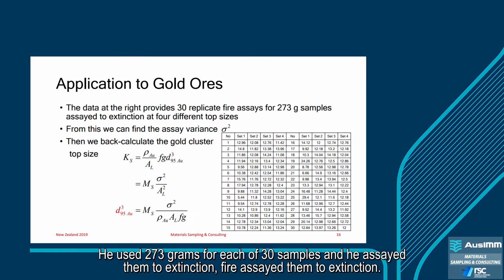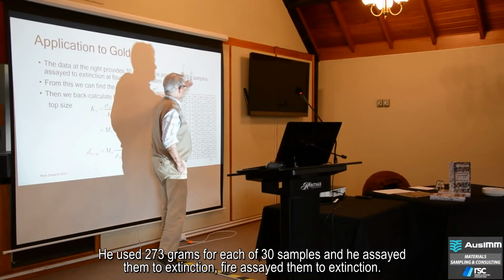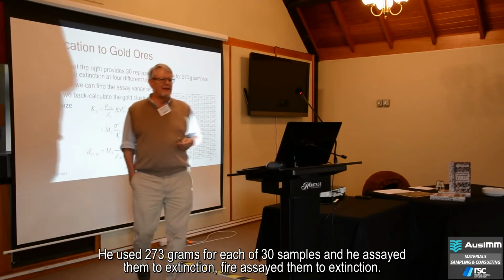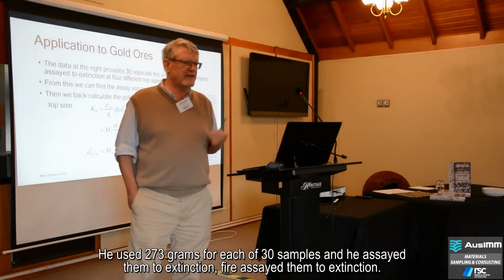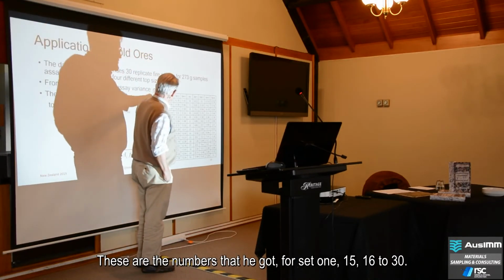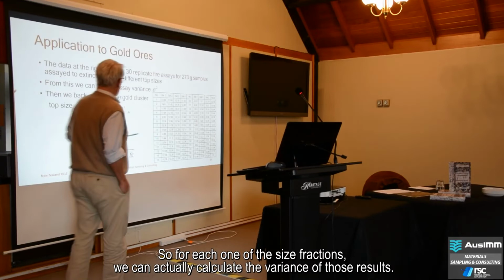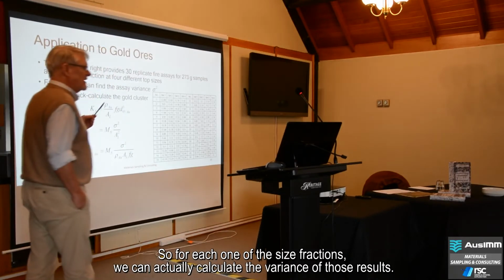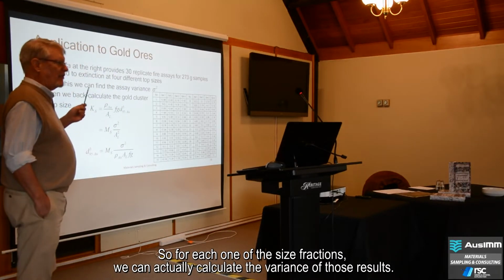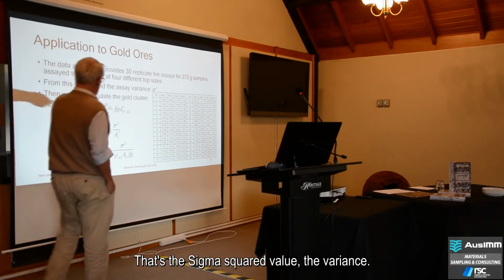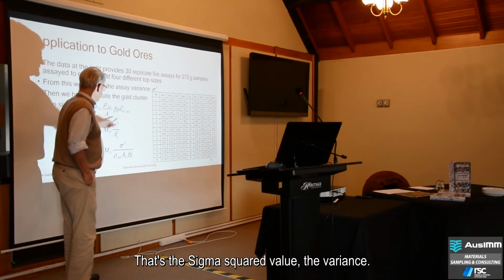He used 273 grams for each of 30 samples, and he fire assayed them to extinction. And these are the numbers that he got, for set 1, samples 1, 2 through to 30. So for each one of these size fractions, we can actually calculate the variance of those results. That's the sigma squared value, the variance.